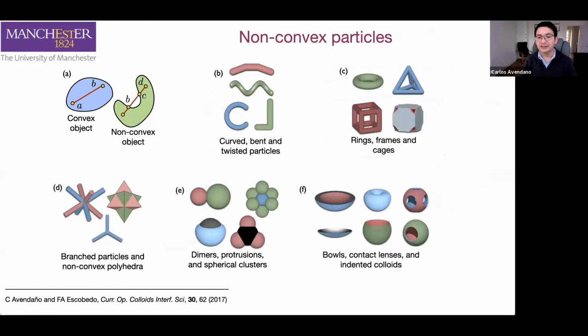One possibility to do that is by using what we call non-convex particles. These are particles that are highly irregular, and there are several examples in the literature that have been reported recently. They can go from particles that are sort of bent, like imagine taking a cylinder and bending it slightly, to particles that look more like rings or frames, or particles that look like branched objects, and so on. All these particles have a common feature, and that is that they do not pack very efficiently. Imagine putting two objects like this together; you know that they are not going to pack very well. So the idea that we had is, can we take that as an advantage and see what kind of structure we can observe by changing the degree of non-convexity in the systems.